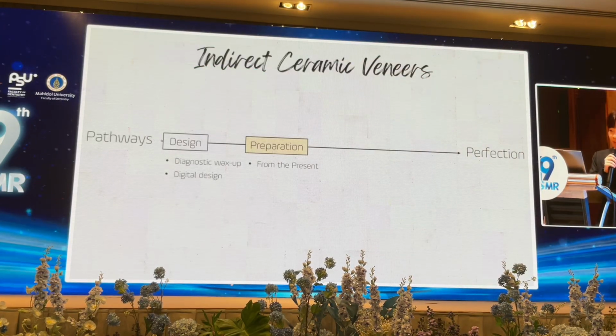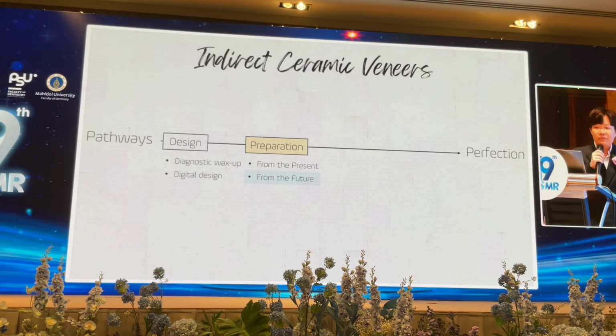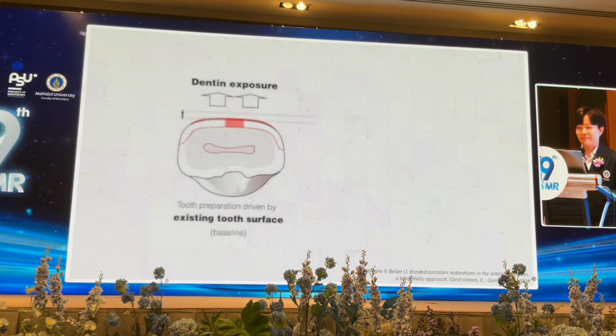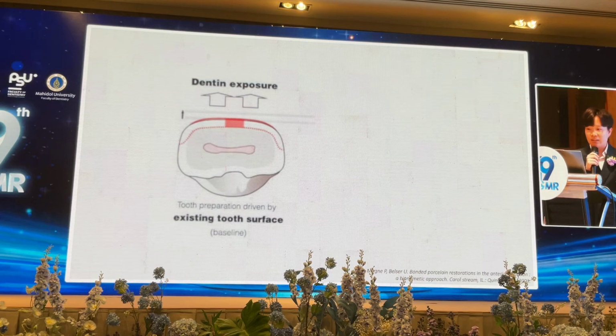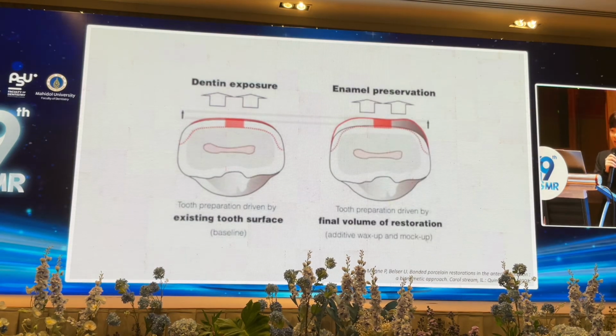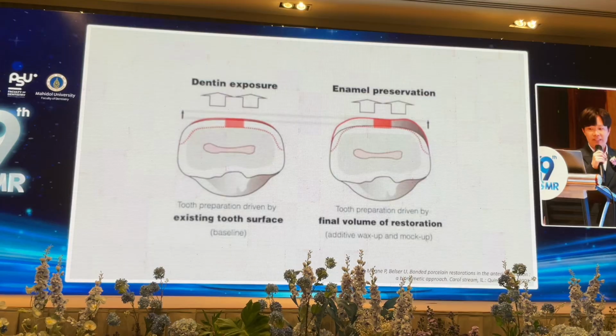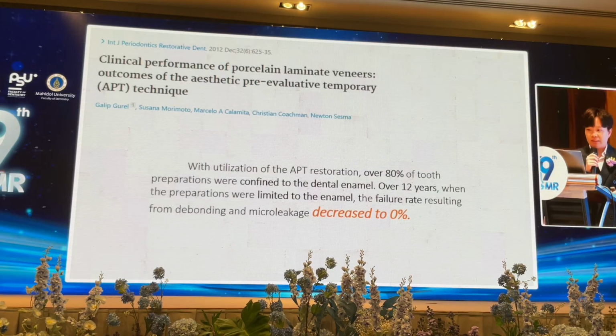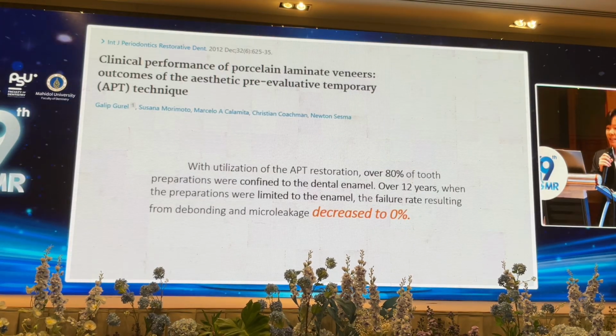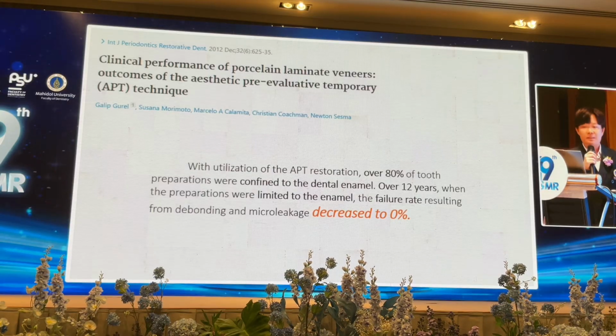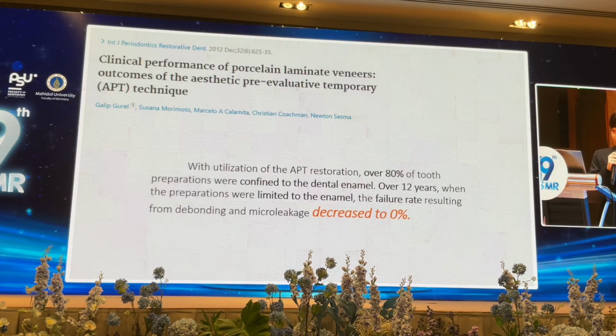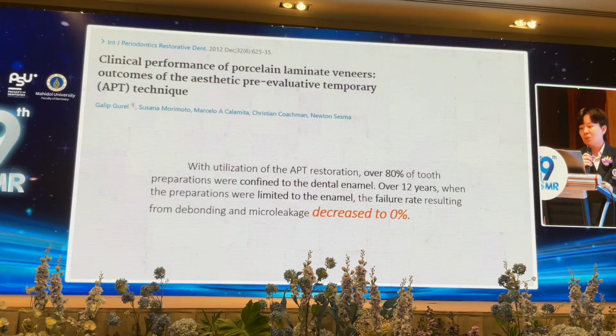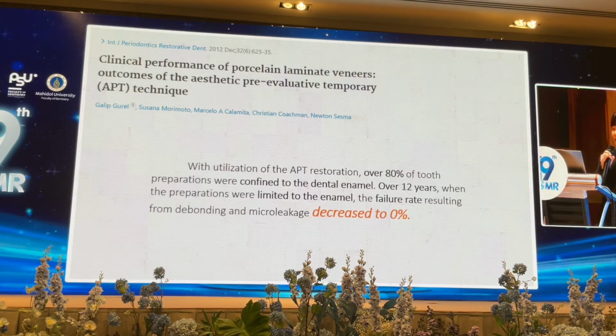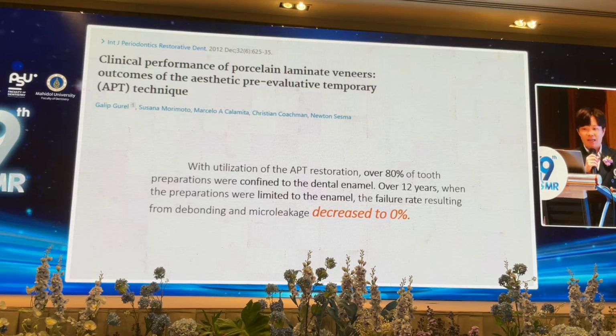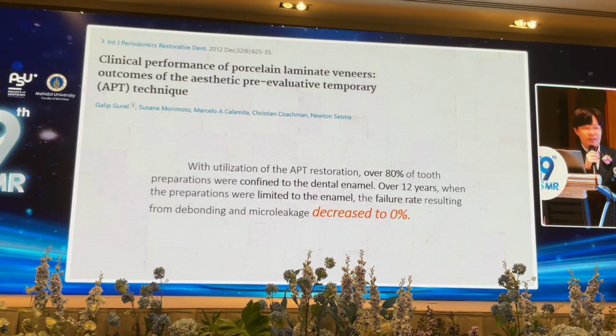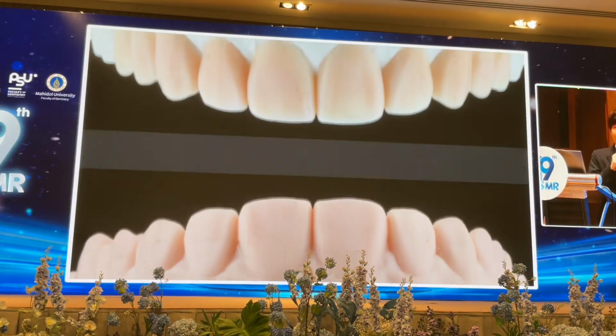Moving forward, we now use "prep from the future." Instead of following the existing tooth surface, the preparation is guided by the final shape and volume of the veneers. And this approach is applied with the APT, or Aesthetic Pre-evaluative Temporary technique, by Dr. Galip Gurel. With this approach, we can ensure that the veneers sit entirely on enamel, and remarkably, a 12-year follow-up shows a 0% failure rate.